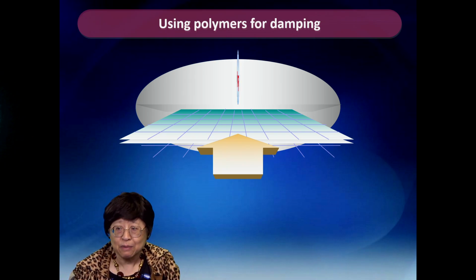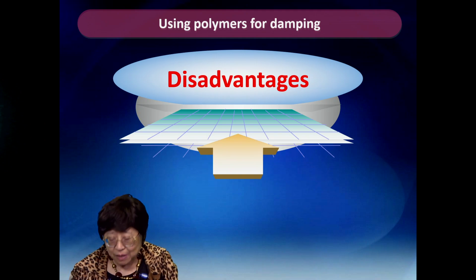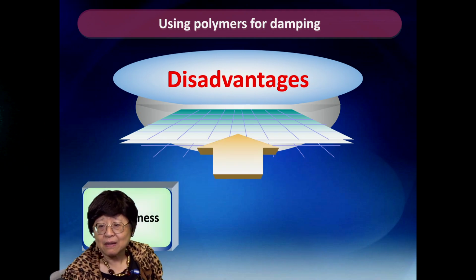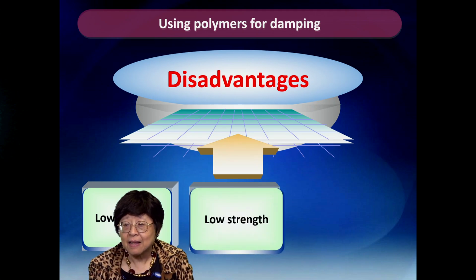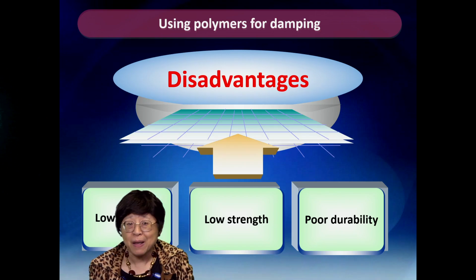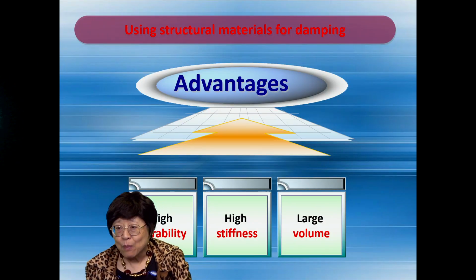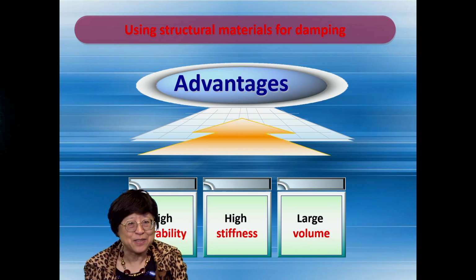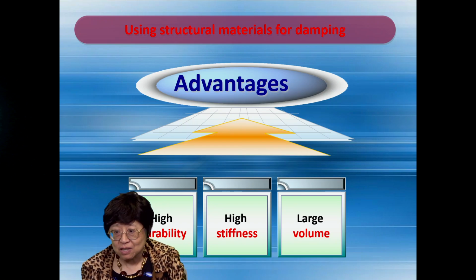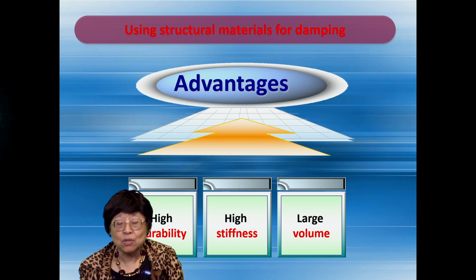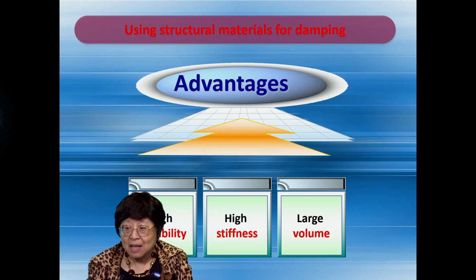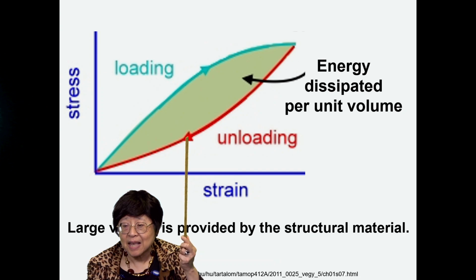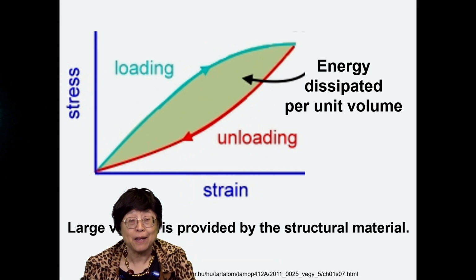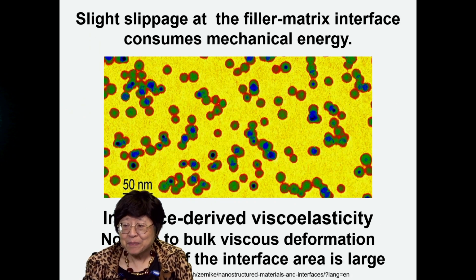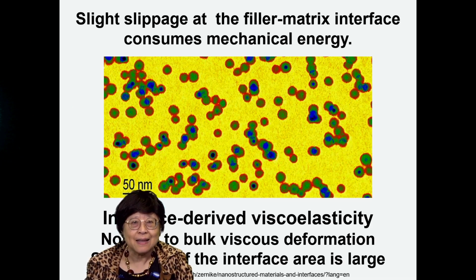Now, using polymers like rubber for damping is very common, but there are serious disadvantages because polymers have low stiffness, low strength, and also poor durability. Our rubber band becomes brittle after a while. However, using structural materials for damping, something I dreamed of, has quite a lot of advantages. They have high durability, high stiffness, and also large volume. This is a structure, so large volume. And this hysteretic area is actually the energy dissipated per unit volume, so having a big volume really helps. But I have to come up with an alternate mechanism for providing that damping.